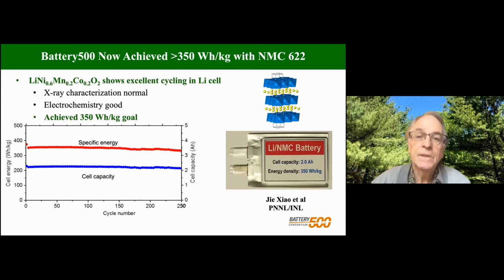So I just want to show you the status of the Battery 500 project. For the first 2 years, we used 622 as our standard, and everybody in the project used the same material from the same supplier. This material has very good electrochemistry, and our goal a year ago was to meet 350 watt-hours per kilogram, and you can see we attained this fairly easily over 250 cycles, and now it's many more cycles. The capacity is retained very well. And I should say there's no fudging the data here. After the cycling was accomplished, the cell was actually weighed, the volume measured, so we know exactly what the energy density was. And the volumetric energy density of this cell was just over 700 watt-hours per liter. And these data were collected by my colleague Jie Xiao at Pacific Northwest National Lab in conjunction with Idaho National Lab.